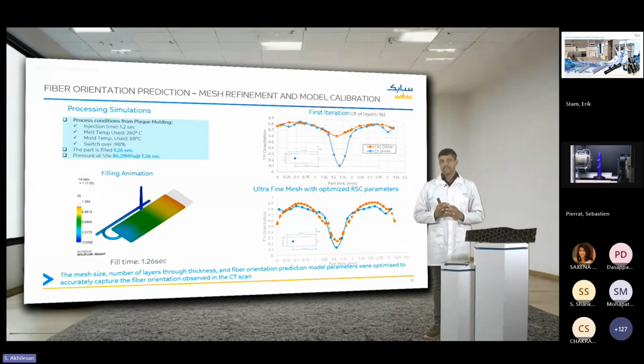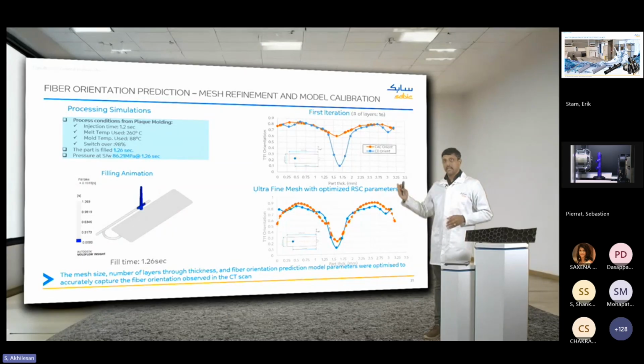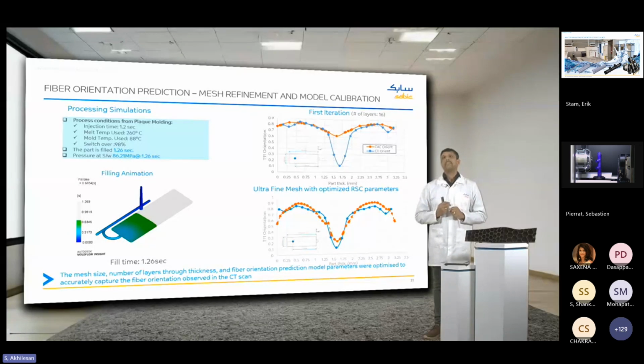When we have done all of this, we then predict a fiber orientation. In the initial stage, it would look as on top. The blue line denotes the experimentally observed orientation at the end of fill location that was measured by Sebastian in the lab. Now, there's a big gap. In order to calibrate the fiber orientation prediction models, we then tweak the constants in this model to better match the experimentally observed fiber orientation. So this is the first step.